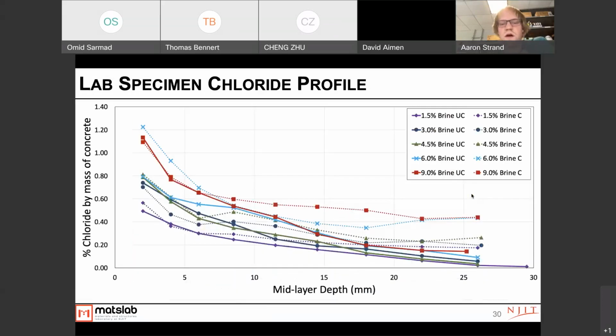So for the laboratory specimens' chloride profile, we can see that there was an increase in the amount of chlorides as the chloride concentration was increased for each of the specimens. But what's interesting to note is that near the surface for most of the specimens, the uncracked and cracked specimens did have fairly similar values, though at the depths closer to the reinforcement, the cracked specimens continued to have a much higher level of chloride content than the uncracked specimens. And near the reinforcement, the cracked 1.5% brine ended up actually having a higher chloride content than the 9% uncracked at this depth, indicating that the presence of the crack is very highly likely to increase the amount of chloride that we can see in it.